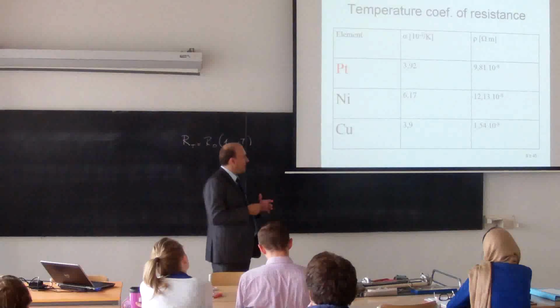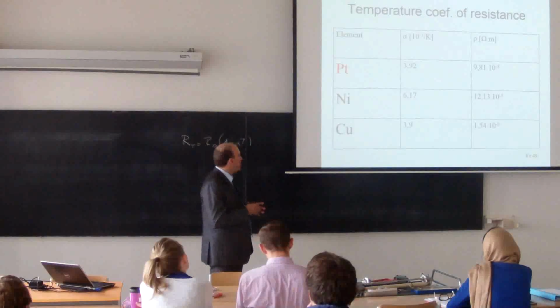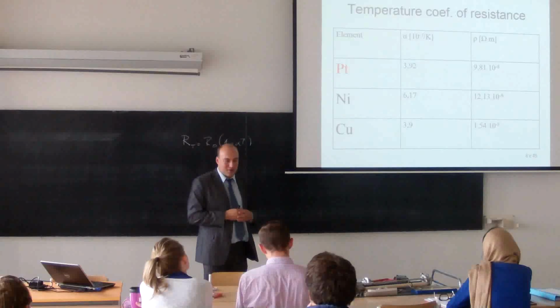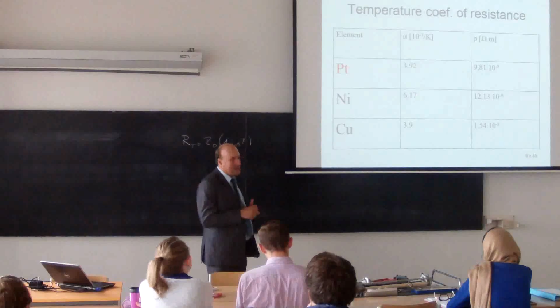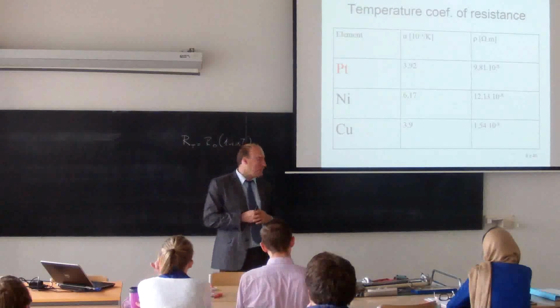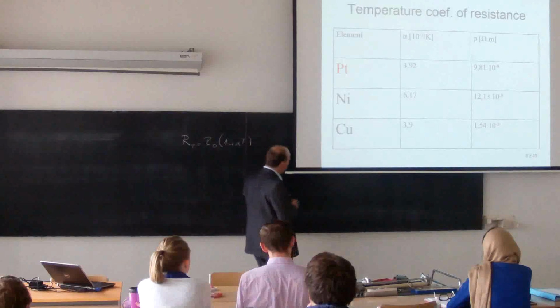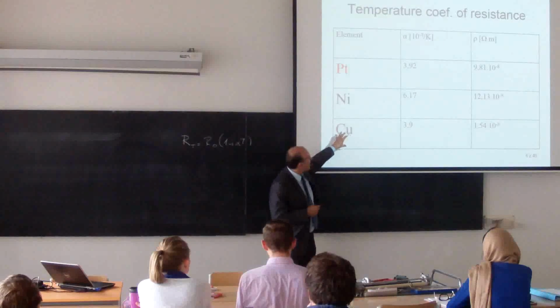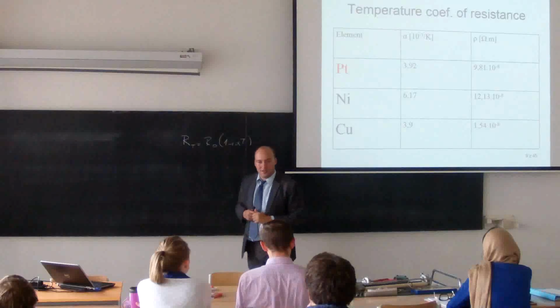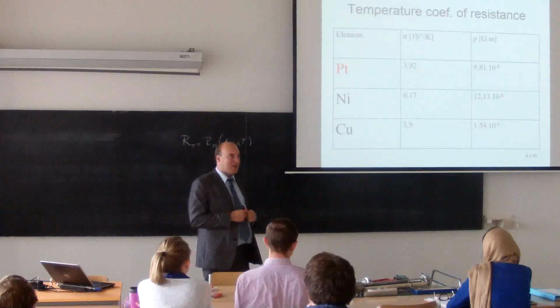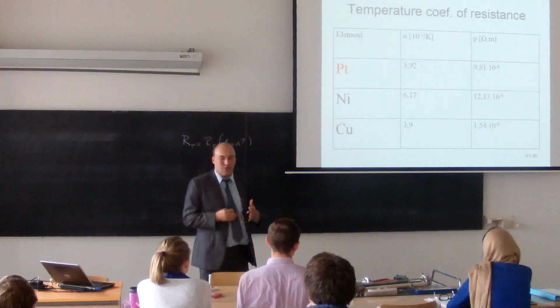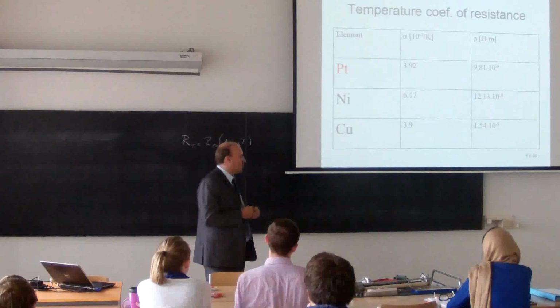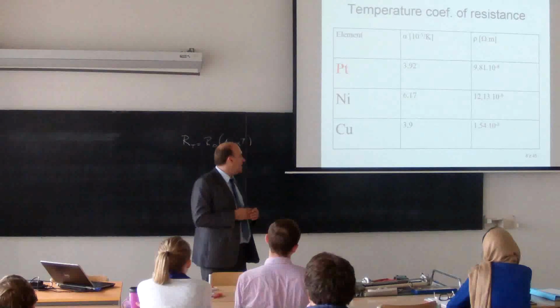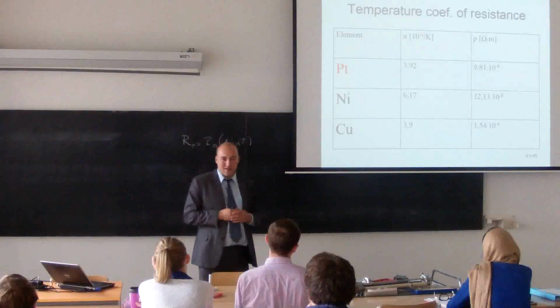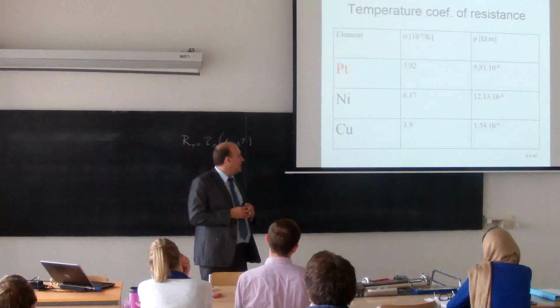We will see that there will be more problems with nickel than platinum. So I will tell you that platinum is great, but it's expensive. If you want something cheaper and buy nickel, you will have more problems. Also, copper. Copper has approximately the same sensitivity as platinum, but we will see even more problems than with nickel. So if you want something really cheap, you can use a copper sensor, but it will last only a short time.